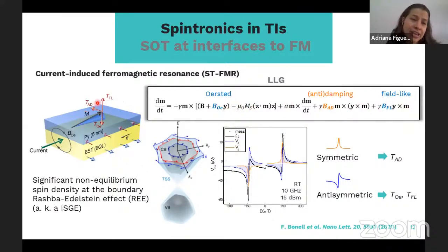And then you have here a diagram of those different contributions, those different torques that are acting onto the magnetization of the ferromagnet. Depending on the component of the ferromagnetic resonance that you're analyzing, you have the symmetric component, which is more related to anti-damping torques. The antisymmetric component has two kinds of contribution: one is the Oersted-like torque, and the other is the field-like torque. As you see, they can even be opposite to each other. And what is the Oersted-like torque? The Oersted-like torque is the one that arises just because you have a current passing through your system, through your metallic system.